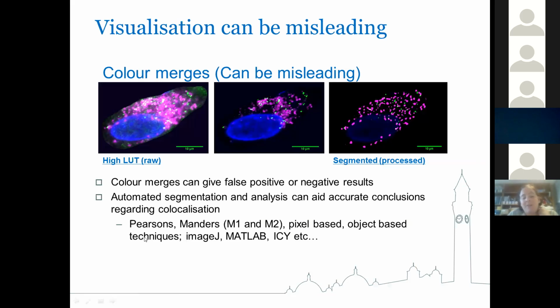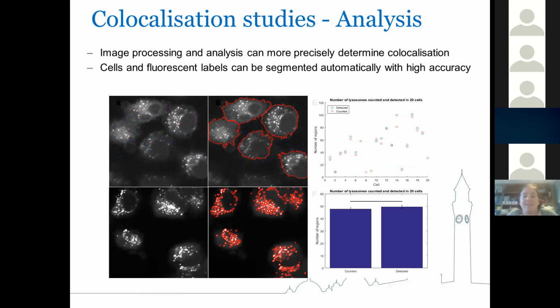So we also did various statistical tests, so Pearson's and Manders, to really understand the correlations between each of the different dyes from the endocytosis pathway with the particles. And again, we automated the process to remove user bias and to make it much more accurate. Both the cells and the fluorescent labels can be segmented and automated, and then we can look at, for example, the number of lysosomes that were counted and detected, so we can confirm that everything that we're seeing manually is counted by the software as well.